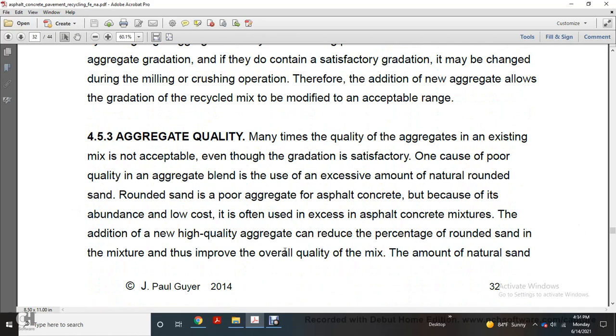Therefore, additional new aggregate is added so that the gradation of the recycled mix is modified to within the acceptable range. Aggregate quality: many times the quality of the aggregate in the existing mix is not acceptable, even though the gradation is fair and satisfactory. One example of poor quality is an aggregate blend with an excessive amount of natural rounded sand. It is a poor aggregate for asphalt concrete, but because of its abundance and low cost, it is often used in excess in asphalt concrete mixtures. Addition of new high quality aggregate can reduce the percentage of rounded sand in the mixture and improve the overall quality of the mix.